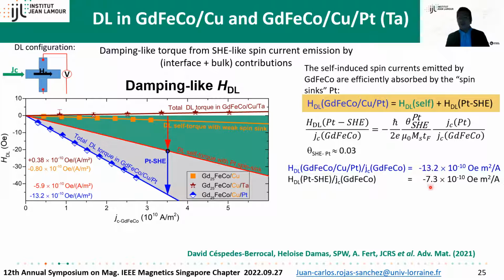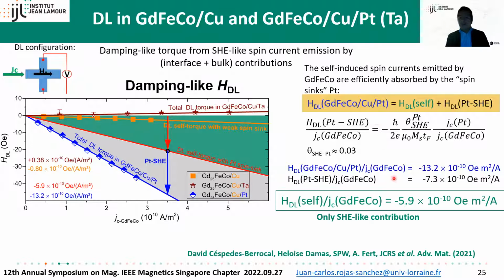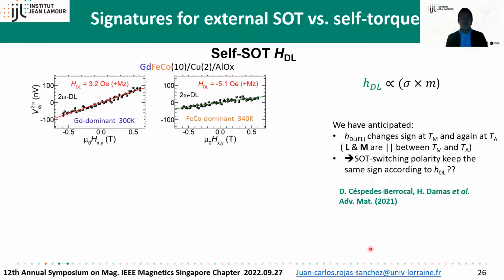Now we know these two terms, and we can compute the contribution from the self-torque. Simple, and interesting, we can see that it's also large, on the order of about 10 to the minus 10 meter squared over ampere, comparable with that of platinum, slightly smaller, but comparable. So it is very interesting to exploit this self-torque. And that is what I wanted to show you in the second part, the main result we have reported in this recent work. So now let me go a little bit beyond that.